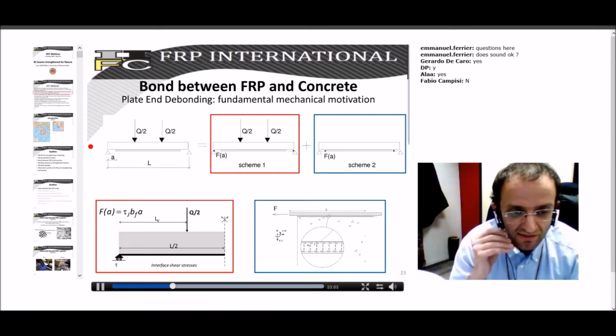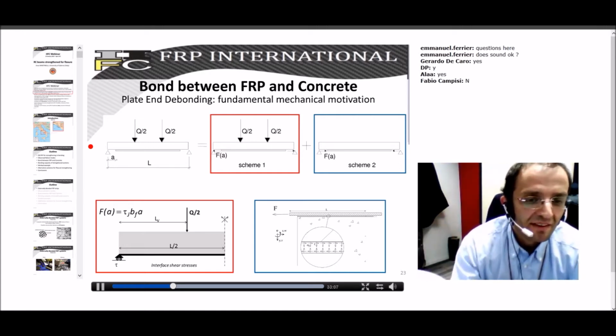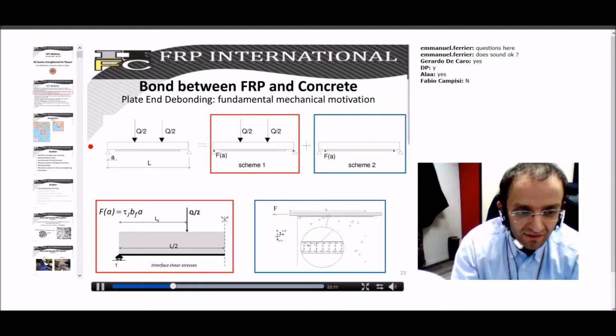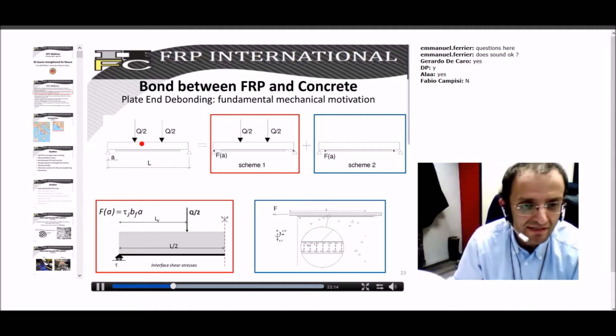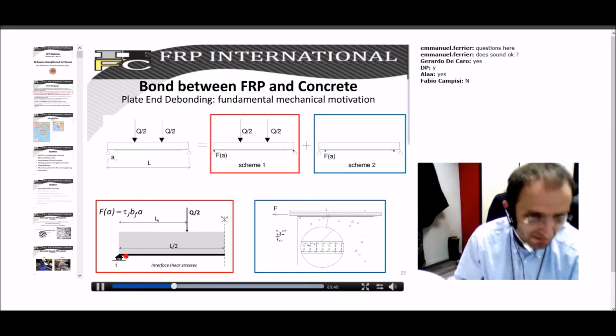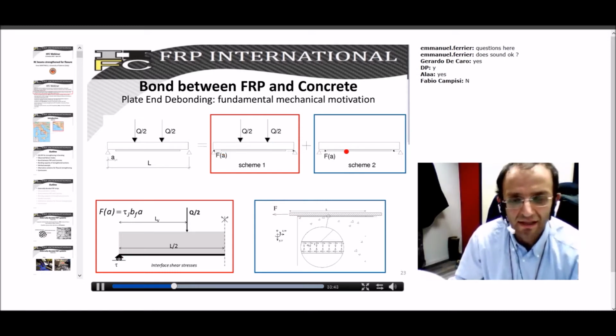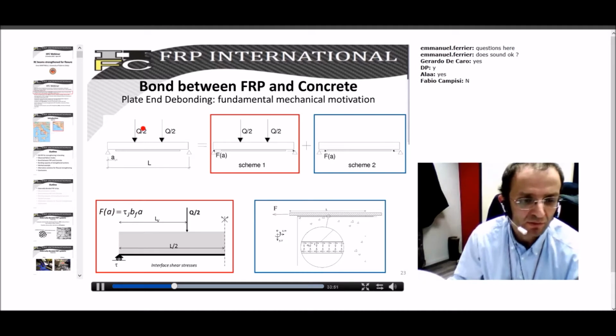Well, we are assuming that the system is linear, at least so far. So we can consider the superposition of effects. We can see that this system is indeed equivalent to a system like this, in which we apply a force Fa, which would have been the same force developed in the case of a continuous strengthening, like in this case. Here you have an almost constant tau, so Fa is the integral of this tau, basically tau times Bf times a. So Fa is applied here, and then there is another system with an opposite Fa. If you add this system to this other system, this is equal to this one, and the effects can also be superimposed, because we are in linear elasticity.